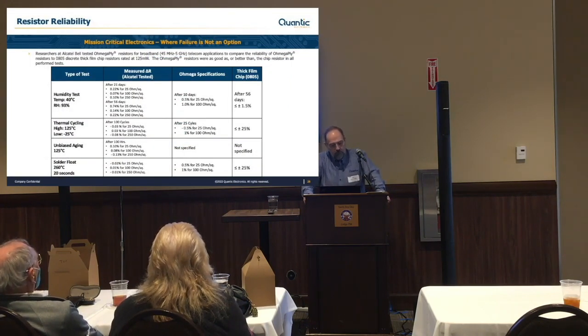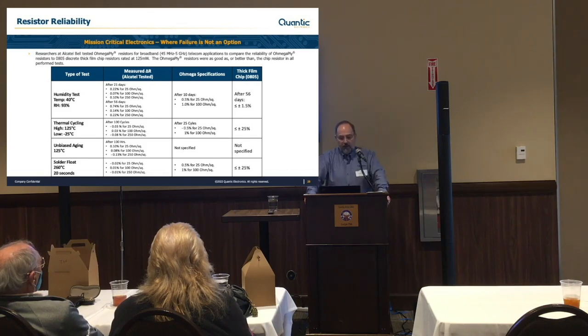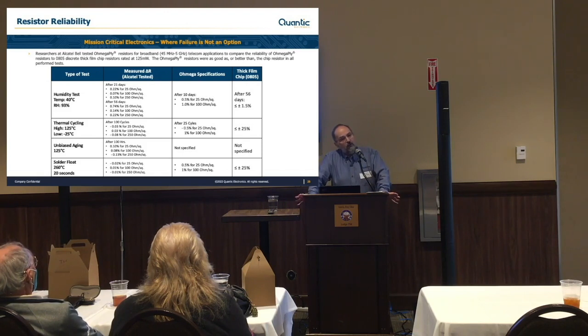So we've done all your typical aging studies, and we've done humidity testing at 40 degrees and 93%. It pretty much doesn't bother it. You have very small changes after both 21 days and 56 days. Again, it all depends. If it's embedded inside the board, you're going to have better performance than if it's on the surface, but it's typically covered with solder masks. If you have a good solder mask, it's not going to be an issue. So again, you don't see very much change.